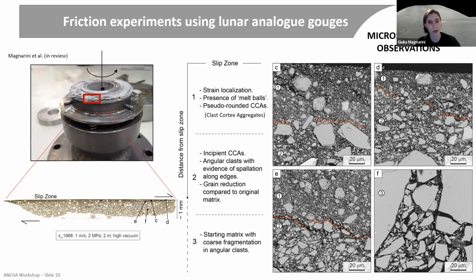And so close to the slip zone, we see a strain localization, and then moving away from the slip zone, we end up finding ourselves with something that looks like the starting matrix with angular clasts. So there are 2 clast fabrics we kind of identified. One we called melt balls, and the other clast cortex aggregate. Next slide, please.